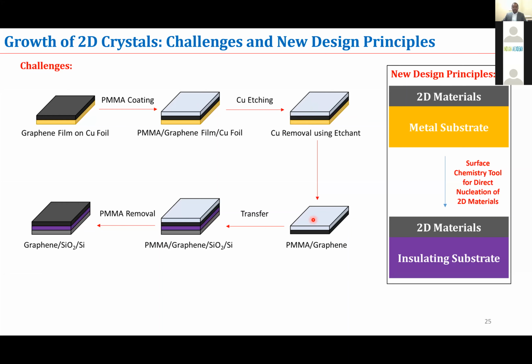And then this polymer, which is a sacrificial layer holding graphene, we need to transfer this structure onto a silicon oxide substrate. And then we can remove this polymer using another organic solvent, for example, acetone. And then finally, we'll have graphene sitting on a silicon oxide substrate, which can be used to measure the electrical conductivity or Raman spectroscopy